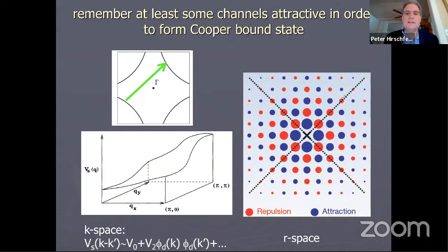Here's a way to see the same thing in two different ways. If you Fourier transform the interaction into real space, you see that if you put the first electron at the center, then the nearest neighbor sites are attractive, and these other sites, the red ones, are repulsive. Nevertheless, there is some attraction present in the system, which the system can take advantage of.